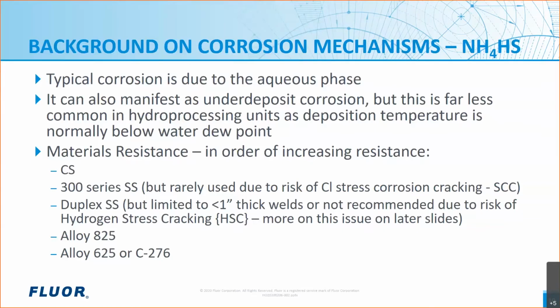So the order of upgrading materials would start from carbon steels. 300 series stainless steels have a much improved ammonium bisulfide resistance, but they're still rarely used due to the risk of chloride stress corrosion cracking, another mechanism that can occur. Now, duplex stainless steels have been widely used and are definitely excellent for resisting pretty severe conditions of ammonium bisulfide corrosion. But again, another problem started occurring. There's been a number of failures at welds due to a hydrogen stress cracking problem. We'll talk more about this later, and I have more slides on this at the very end of the talk.